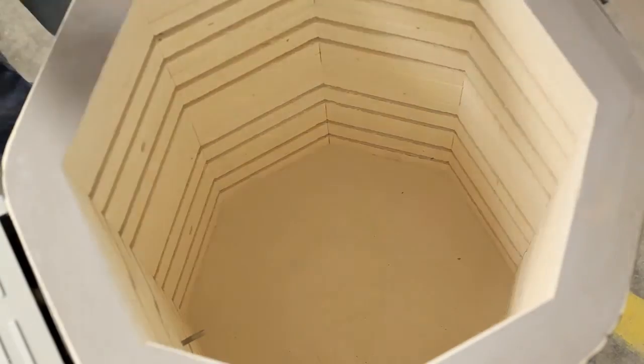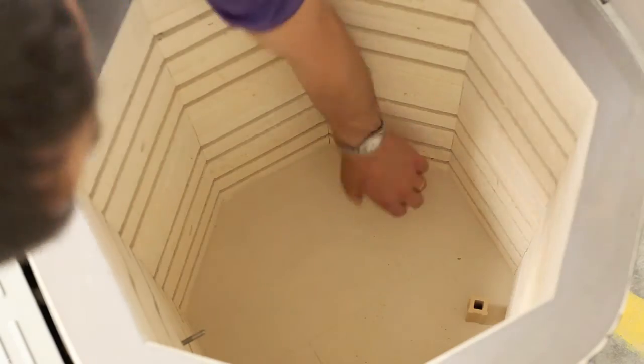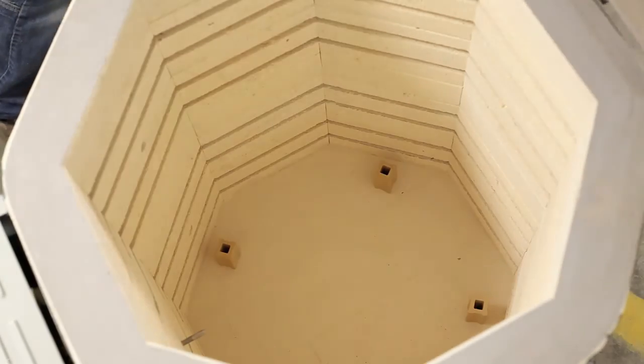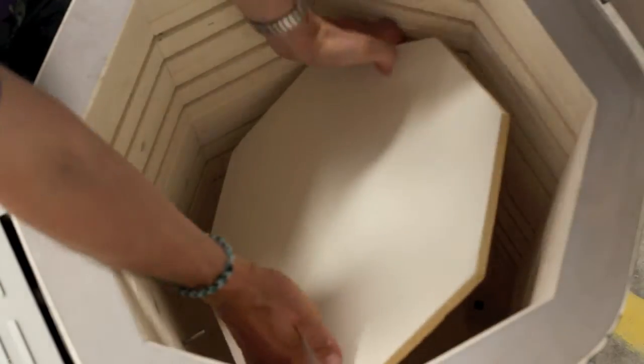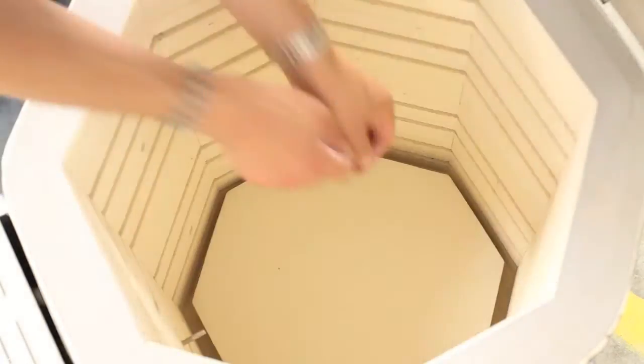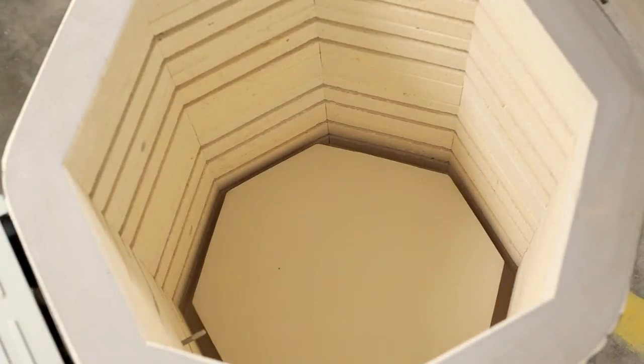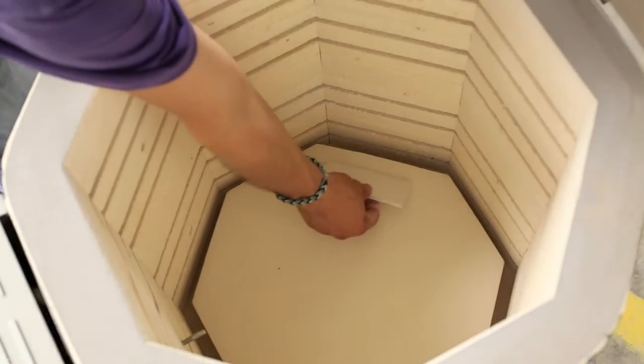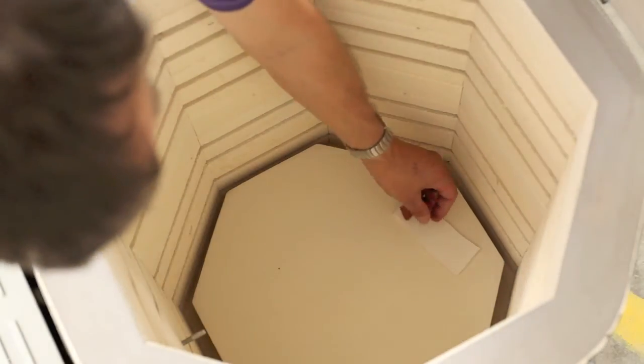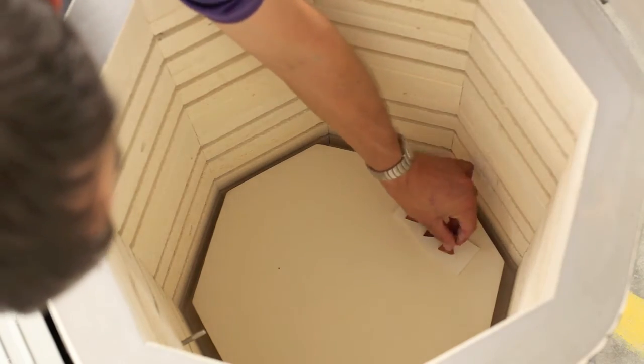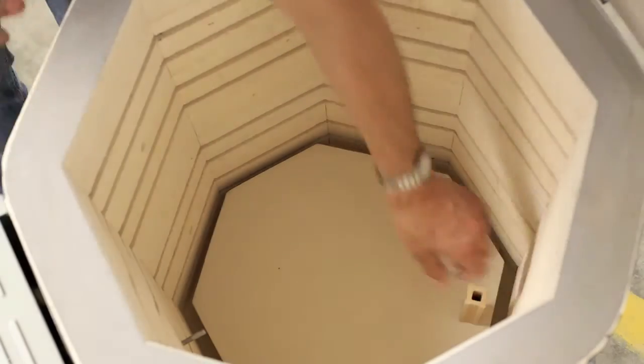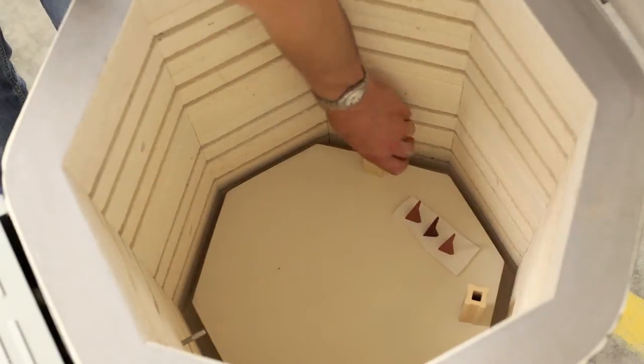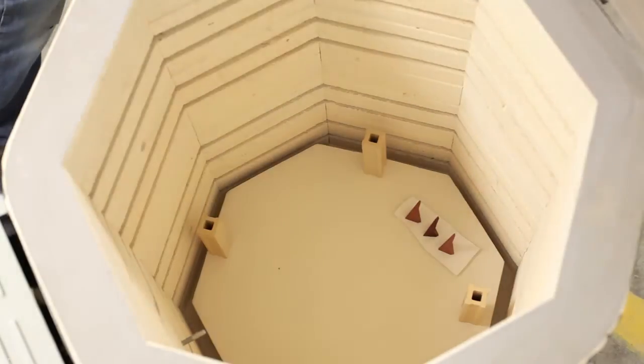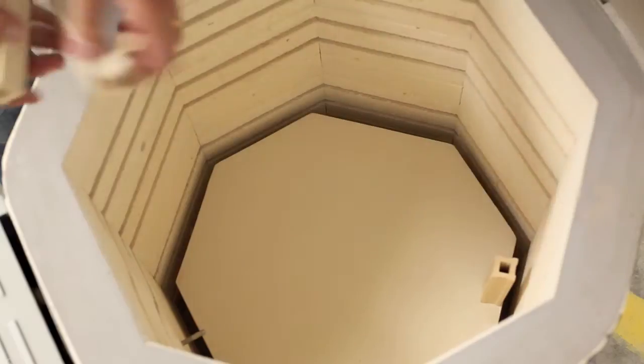For the first firing, we suggest going to a cone 01. This is likely to be a higher cone than you'll normally be firing to. This firing will test that the kiln is fully functional. It also tests your electrical connection is sound, and it will also be putting a protective coating of oxide on the heating elements, which help prolong their life. And most importantly, it allows you to see exactly what happens during a firing, how hot the kiln gets, what noises the kiln makes during the firing, and how long the kiln takes to heat up and cool down.